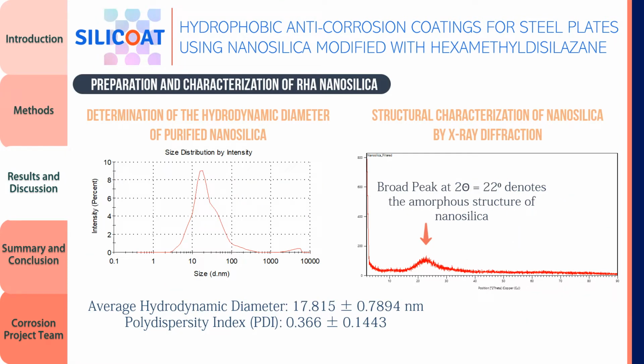For the results, the characterization showed that the nanosilica was amorphous with a polydispersity index or PDI of 0.366 plus or minus 0.1443 and a hydrodynamic diameter of 17.815 plus or minus 0.7894 nanometers.